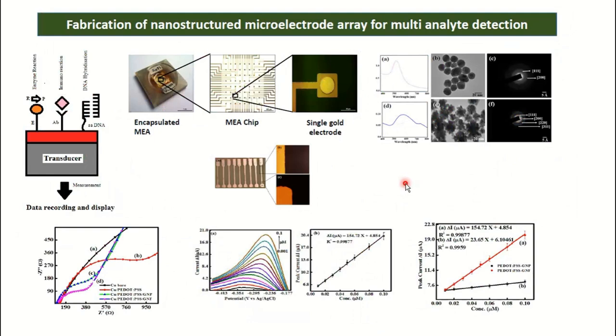So then we also worked on, as I mentioned, bioelectronics. I fabricate my MEMS electrodes by myself. I have my own fabrication facility, and we use these kinds of biosensors where antibodies and aptamers are used. With these different kinds of biomolecules, we can immobilize them on these electrodes. And what we have found is that with these planar electrodes, if we want to increase the sensitivity, gold nanostructures play an important role. The gold nanoflower and the gold nanoparticle were immobilized on top of this planar electrode.